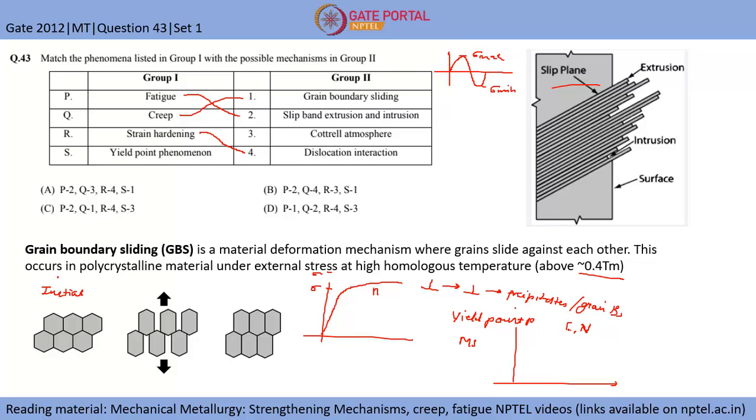Let's say these atoms form an array of five or six atoms in a single place, so the dislocation will have more resistance to its movement. So the initial yield stress will be higher, and then it will drop when the dislocations move away from carbon and nitrogen. Then some serrations will take place, and after that the normal hardening behavior will continue.